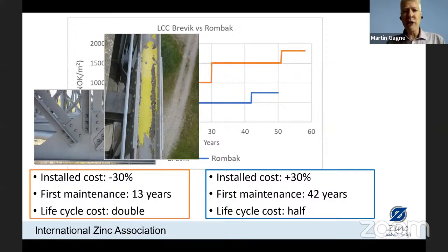If we use the same criteria of 5 to 10% of red rust evident on the structure, this could probably be left for 100 years before we even start to see red rust, because after 42 years, we have some damage to the top coat, but the mid coat is still in play. The zinc would have to be exposed and consumed before we start to see red rusting. So significantly longer life with the duplex coating.